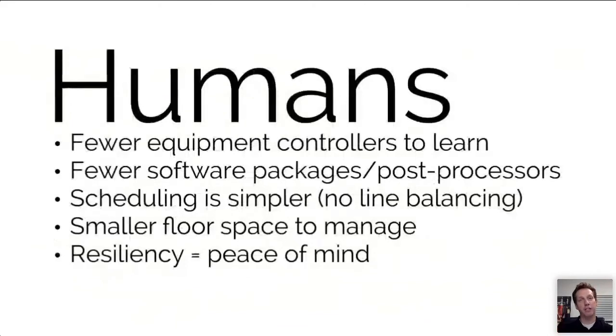And lastly, if we look at the human aspects of this, you go from what largely involves manual moving of lots of parts all around. These jobs are high pressure jobs, and the consequences of making a mistake are very, very high. To systematize it in a digital environment allows systematic correction to be much easier. We actually did a different study with Cummins, and we looked at where many of the mistakes happen and where the rework is caused from. And we found that by automating, up to 95% of the mistakes could be omitted or at least systematically taken care of, which was really a revealing number.